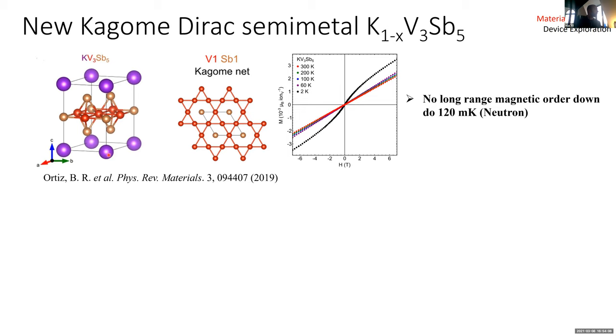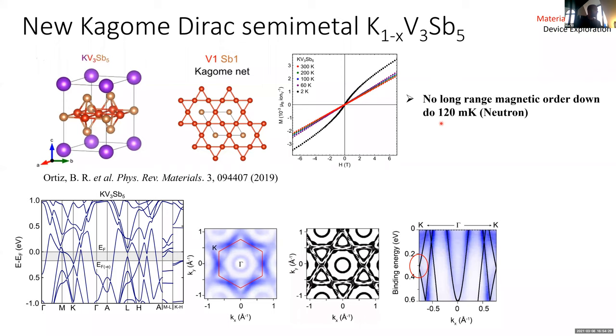So it's very nicely exfoliatable, and it's actually very stable to exfoliation, which is nice. And from there, in magnetic investigations, it doesn't appear to have long range magnetic order down to low temperature. And through our investigations, we said, okay, let's take a look at the electronic structure. So we took their samples and we did some ARPES and found that it matches the electronic structure pretty closely, and that you end up with these pretty sharp linear dispersive bands. It should have, let's say, low effective mass, high mobility.